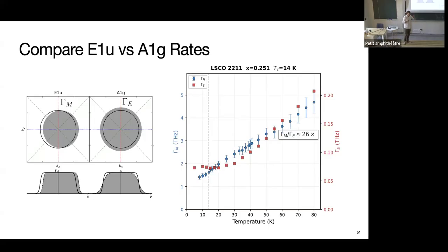Coming back to what I said about scatterings, most of the scatterings that take away momentum from the system don't take away energy from it. So that's the point that you can take away from this. The other point that I will make is that this is linear in T over this whole range, and then this, of course, just continues on up to even higher temperatures.